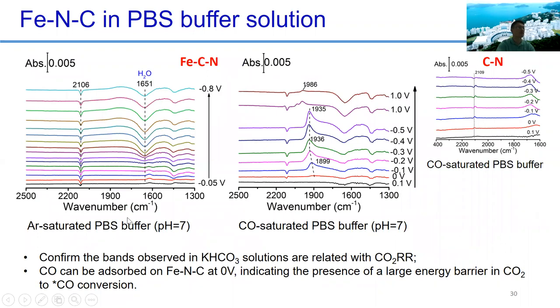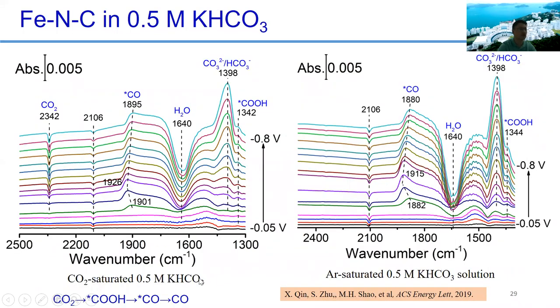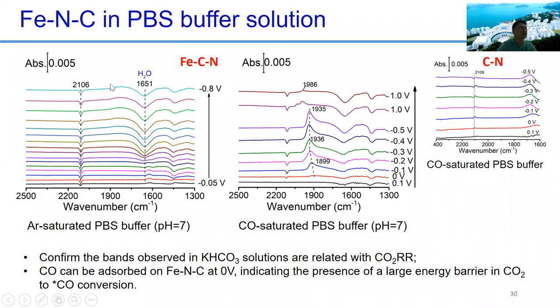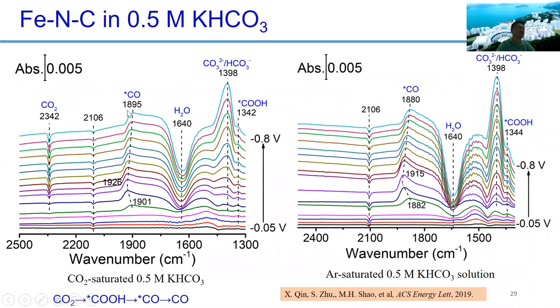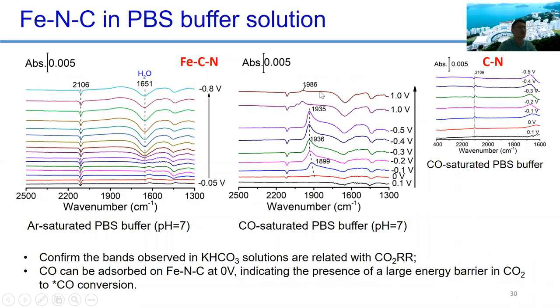We also did the testing in the PBS buffer solution, pH 7. So in this case, there's no carbon source. The electrolyte doesn't have the carbon. You can see that on the surface, we don't see any carbon monoxide signal. And for the CO saturated PBS buffer solution, we do see this CO absorption. So that means this band that we found in the bicarbonate solution is actually from the surface CO.